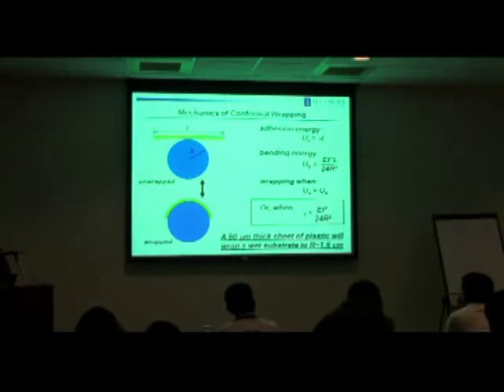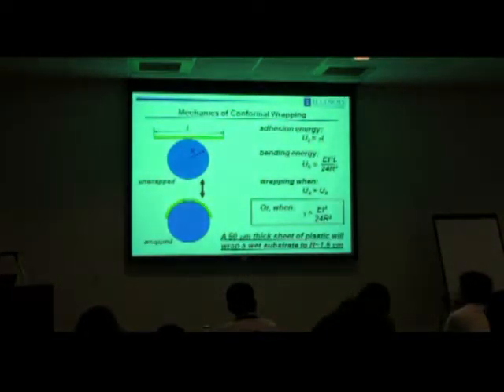So that becomes a problem in mechanics that has a deceptively simple apparent solution, which is you can look at this system, you can ask when will a sheet of plastic wrap a cylinder with a radius of curvature given by R. And that just happens when the bending energy is lower than the adhesion energy. That is to say, this thing will bend more easily than the energy associated with the contact of these two wet surfaces. So the bending energy is cubic in the thickness, and depends on the radius of curvature. The adhesion energy just depends on gamma, and in this case, this length dimension. So gamma is a given for two wet surfaces.